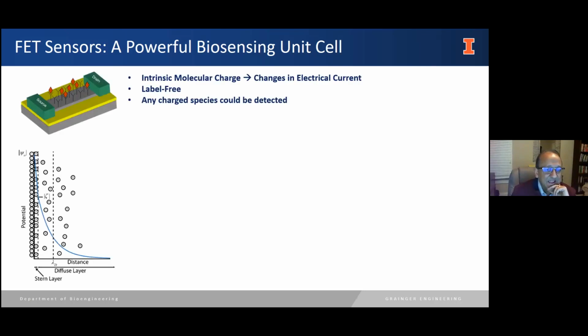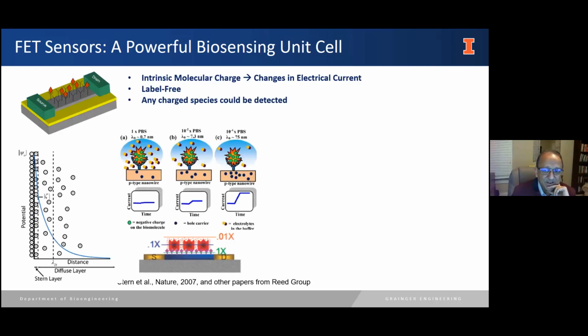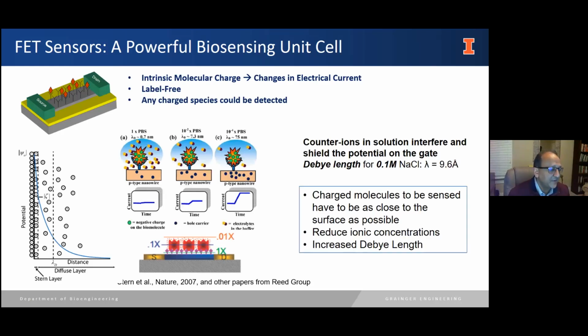Okay, 5 more minutes. All right, so I'll try to just show you one new sensor type that we're pretty excited about. I'll try to go a little quickly if you don't mind. This is the idea of using a field effect sensor to measure a biomolecule by measuring the presence or absence of charge. DNA and proteins have a net charge, or an intrinsic dipole, that could be measured, or a charge perturbation can be measured when you bring the molecule close to a silicon transistor. So you use a field effect sensor, and this is how commercially available pH sensors work.